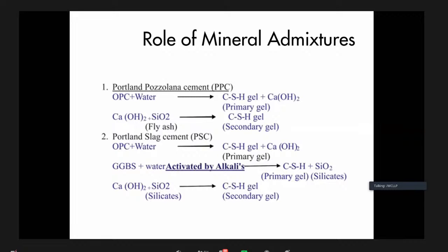That means now we will have to utilize this calcium hydroxide, which has come as a byproduct of the primary reaction, in some different method. So what we do is use these mineral admixtures. These mineral admixtures essentially contain amorphous silica in the form of SiO2. So if you see the reaction at the bottom, this calcium hydroxide in the presence of water will react with SiO2, which are the silicates present in the mineral admixtures, and that will form a secondary gel.